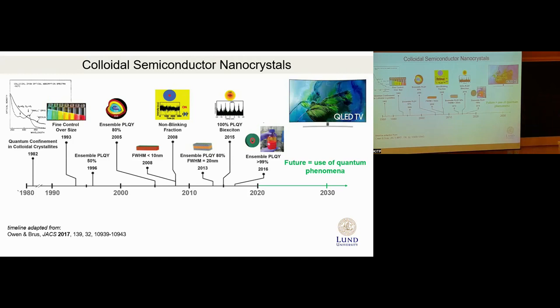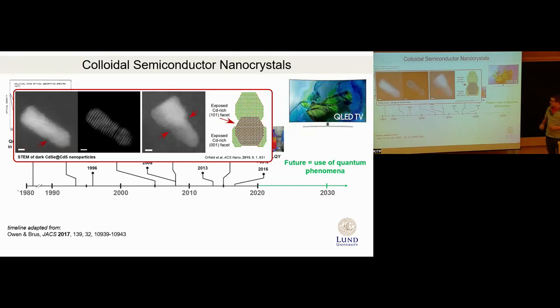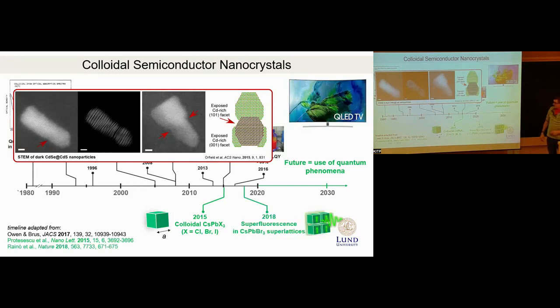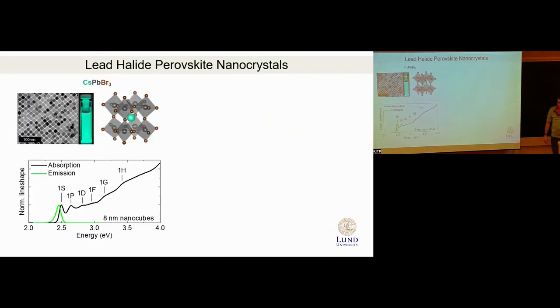One reason is that the most studied materials, II-VI semiconductors, suffer from defects which introduce non-radiative recombination channels. For example, you can make core-shell particles with high quantum yield, but there always will be some defects that will quench emission and prevent the use of these materials in quantum technologies. The situation drastically changed around 2015 when the community shifted their attention to perovskite nanocrystals. Just 3 years after high quality nanoparticles of perovskites were prepared, superfluorescence was reported, which is a remarkable quantum phenomenon. So what are these lead halide perovskite nanocrystals and why are they special?